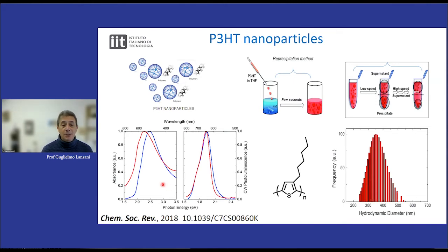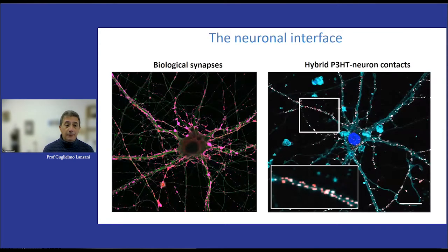And you see here the absorption and the emission spectra, a comparison of nanoparticle and film, and they are quite similar. So at the end, what we obtain is something that behaves pretty much like polythiophene in solid state. And now, when we add the nanoparticles to cells in a culture, here is a neuron on the right, where is the pointer, you see that the nanoparticles with the neuron, they decorate the membrane, but they do not get internalized. That's a very important result that mainly comes from two reasons. One is the characteristic of the neurons that are not particularly keen to internalize things. And the other thing is the size of the nanoparticle and probably the surface charge, which is favoring this docking to the membrane and without internalization.